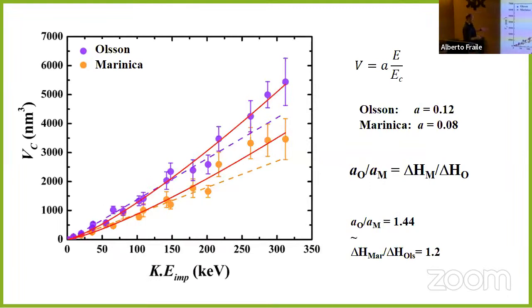The basic thing is this, the volume of the crater. That is what we can compare to with experiments. So the volume is expected to be linear with the kinetic energy, and it is, although it has an apparent deviation for the very high velocity, but it's basically linear, so it can be fitted with this simple formula. The slope here is called cratering efficiency. And we have these two values for the two potentials.